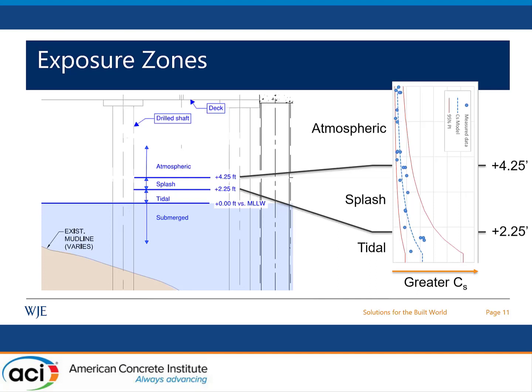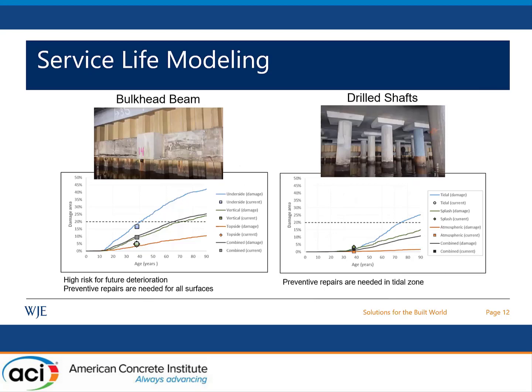And to capture the variability of the surface chloride at a given height, we calculated the prediction interval, and we used normal distribution at each height based on the prediction interval limits. So then we used WJE Castle to perform our service life modeling. And here I'm showing the results for a couple of the elements in the structure, bulkhead beam and drill shaft.